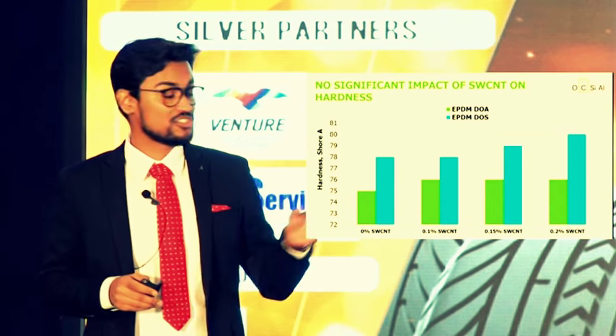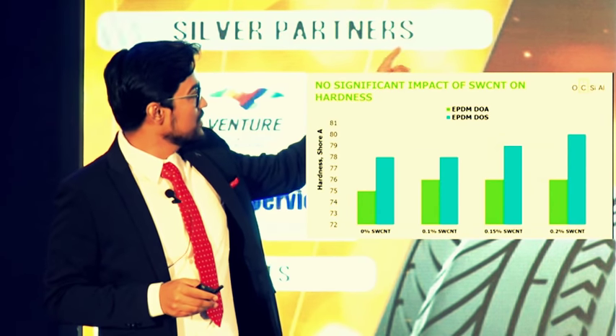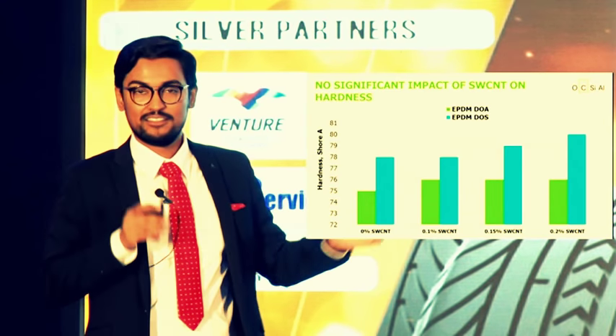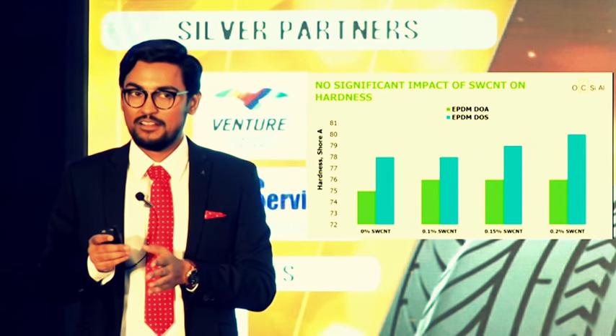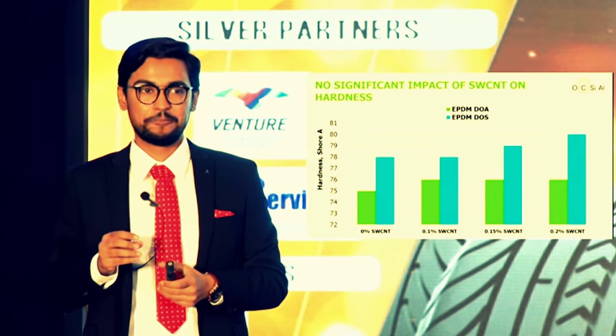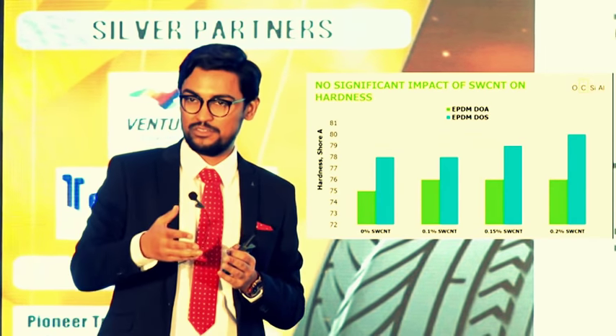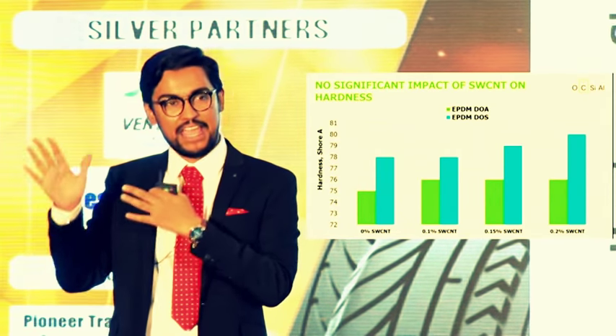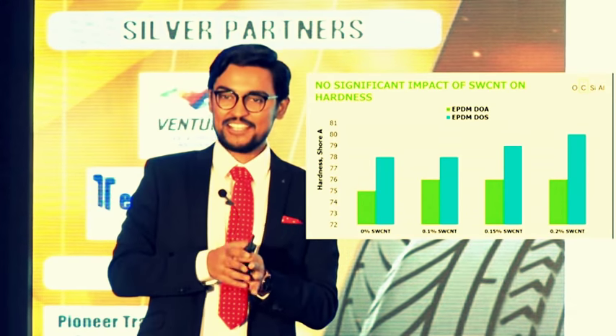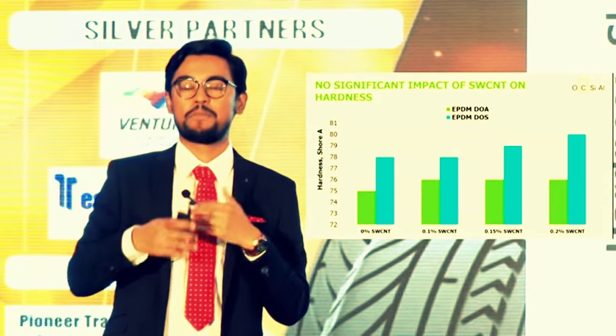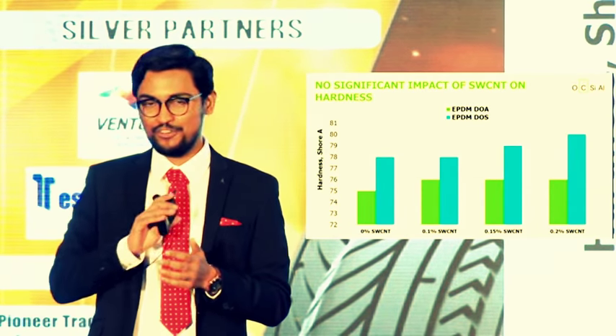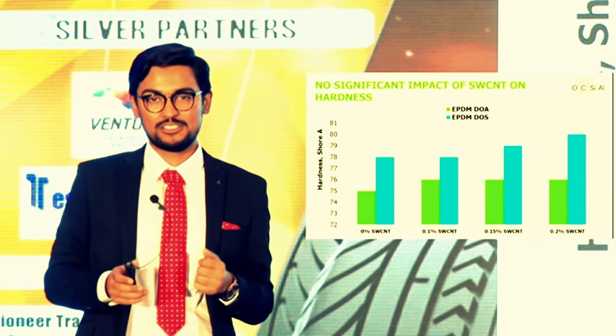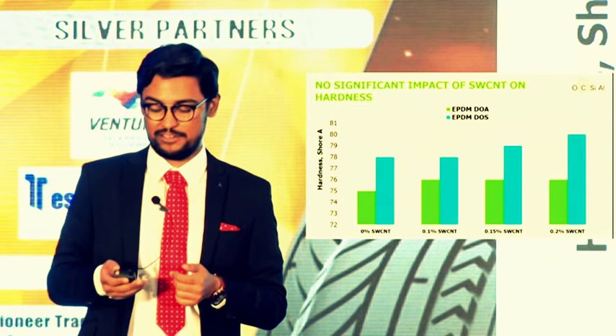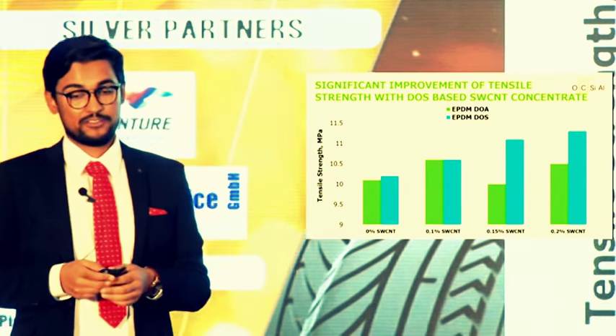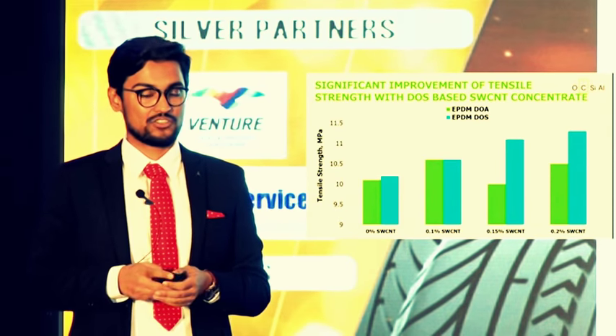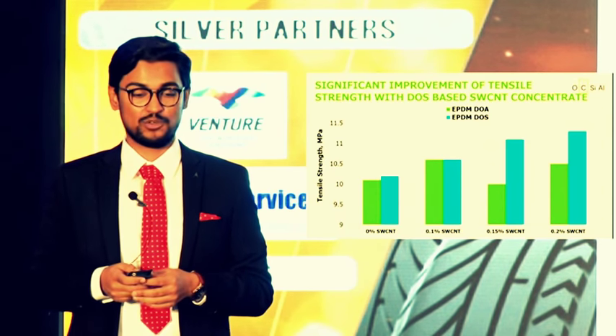You would also find it very interesting to note here that between DOA and DOS, there are different results. Now, this is to be kept in mind that single-walled carbon nanotube alone would not result in an end product. It has to be combined with a compounding technique and carrier. Everything is relevant in that case. Hence, you can see two different kinds of results with two different kinds of carriers. There was a significant improvement in tensile strength of DOS-based concentrate, as you can see.